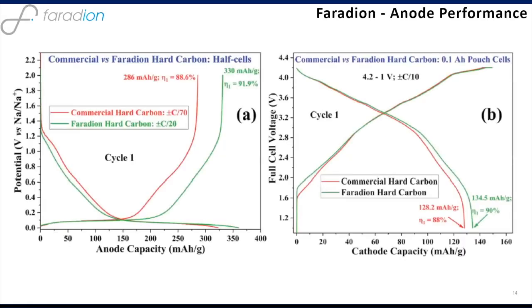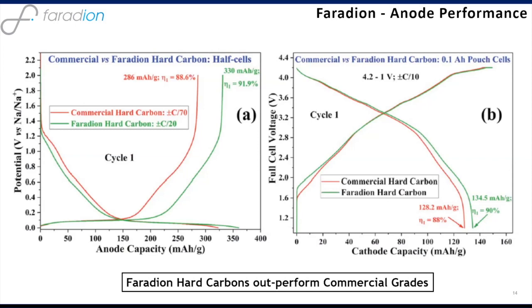In terms of the hard carbon materials, I said to you, most of the negative active materials are based on hard carbon. If you just take a commercial hard carbon, one of the hard carbons that was originally developed for the lithium ion space, it gives you a pretty good performance in a half cell, right? You get close to 300 milliampere hours per gram. But we've looked at huge numbers of precursors and different synthesis methods to make hard carbons. And if you know that the requirements are slightly different for sodium applications over lithium applications, you can develop hard carbons that give you superior performance to the commercial versions, shown here, one made by Faradion.